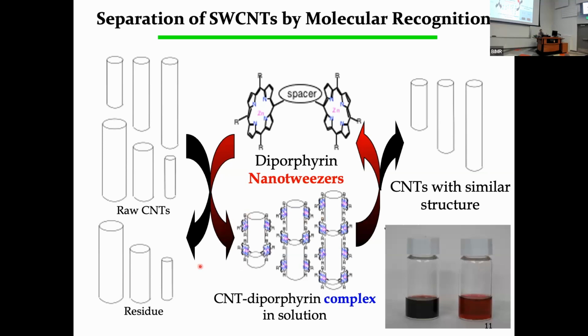We can easily separate them by centrifugation. After separating them, we can change the solvent for the washing process. In the washing process, we can easily recover this host molecule and leave the pristine carbon nanotube with a similar structure. This is our strategy to separate the carbon nanotube through host-guest chemistry.